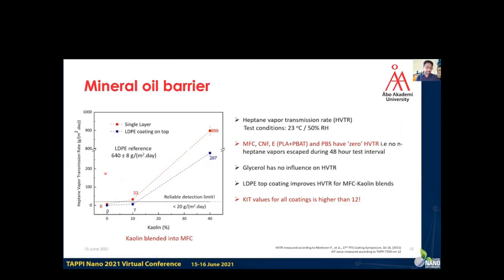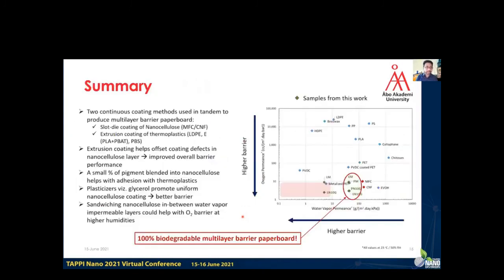LDPE as such does not have any barrier against heptane vapor, but as said before, it fills in any gaps and defects and improves the barrier a little bit. And even 10% clay here, for example, performs much better with LDPE coating on top. We also did kit tests for all the coatings, which give a value from 0 to 12, with 12 being the higher barrier, and almost all the samples have a kit value of 12.